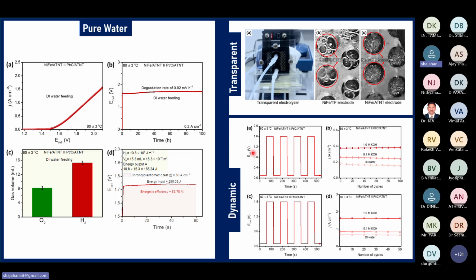And importantly, we also studied how our electrolyzer responds at the industrial scale. Because in the industrial scale, when you connect with renewable energy sources, we know that renewable energy sources always show some fluctuation. So at that time, the electrolyzer should sustain those fluctuations. So that dynamic load has to be sustained. So we also tried our electrolyzer setup with different potential ranges. One is 0.1 to 1.6, another one is 0.1 volts to 1.8. At different potentials, we have tried for different times.